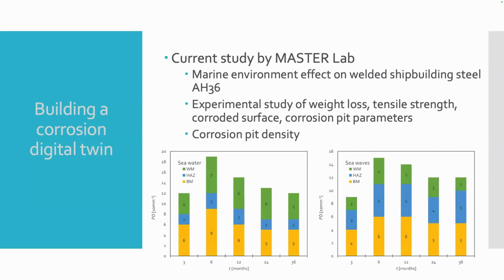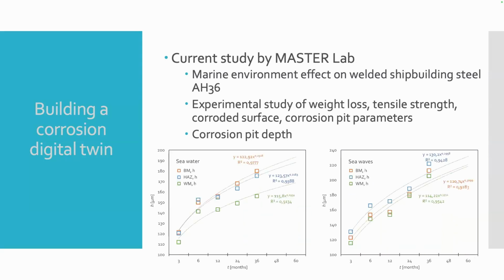And we have also counted the corrosion pits on the control areas, and you can actually see here that the number of the corrosion pits tends to be lower as the time of the submersion increases, because these pits tend to join together and their number is decreasing. Also, we have measured the corrosion pit depth and also fitted some curves to see how well they behave in the periods that are ahead of us.